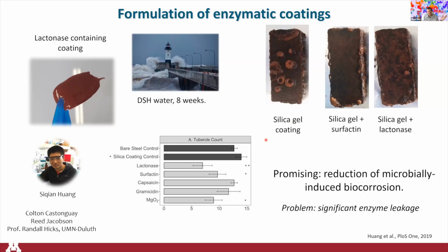And while this is a desired trait, for example, for the biocide-containing coatings that are commercially available, because they need to constantly release that amount of toxic ion to constantly kill the surface microbes, in our case, this is not the case. We want to keep the enzyme in the coating because otherwise nothing is going to destroy the communication molecules of the bacteria, and then they're going to take over, right? So we want to keep as much of the enzyme in the coating for as long as we can.